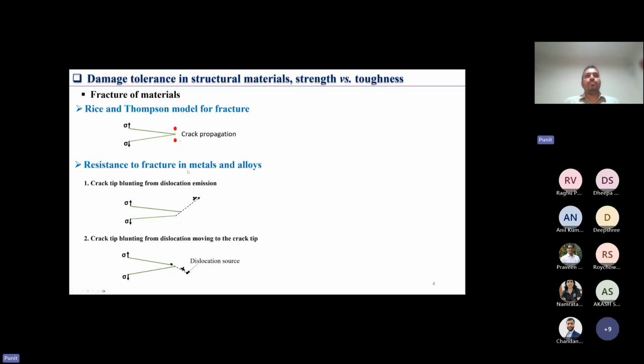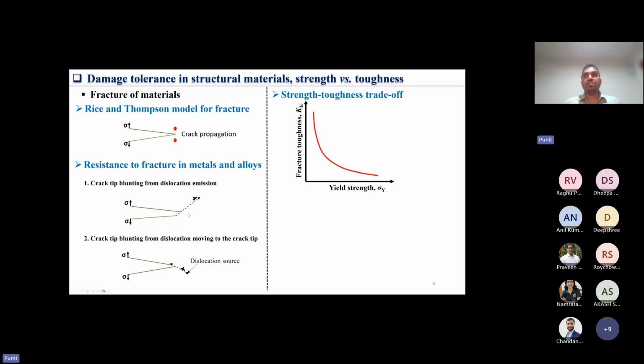But if we look inside metals and alloys, and extend the same model to these materials, then when you apply a stress at the crack tip, instead of breaking an atomic bond, what will happen is that you emit a dislocation from the crack tip, or if you have a dislocation source ahead of the crack tip, it will emit a dislocation and it will end on the crack tip. And as you can see, when you emit a dislocation, or you have some dislocation activity at the crack tip, your crack tip is now blunted, and you need to apply even higher stresses to grow the crack. So this is the origin of the strength versus toughness trade-off that we usually see in metallic materials.